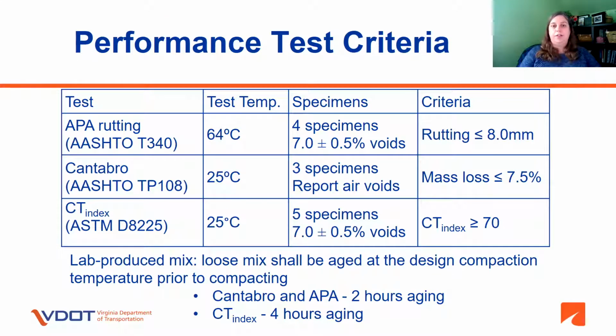The performance test criteria in the special provision are laid out in a table. The rutting test is performed in accordance with AASHTO T340 at a test temperature of 64 degrees C. You'll be producing 4 specimens at an air void of 7 plus or minus 0.5%. The criteria for the rutting test is that it be less than or equal to 8 millimeters. The Cantabro test is performed in accordance with AASHTO TP108 at a test temperature of 25 degrees C. The test is performed on 3 volumetric pill specimens. The air voids are reported, and the mass loss must be less than or equal to 7.5%.